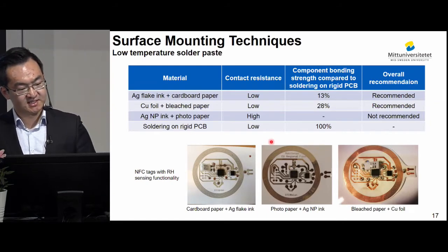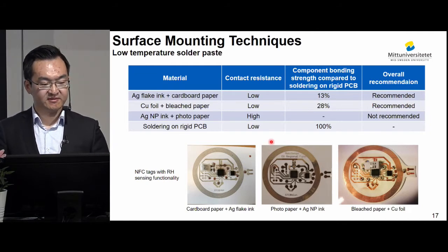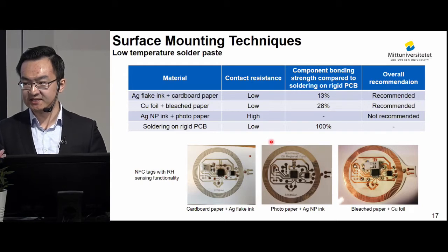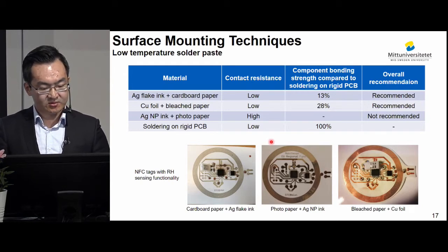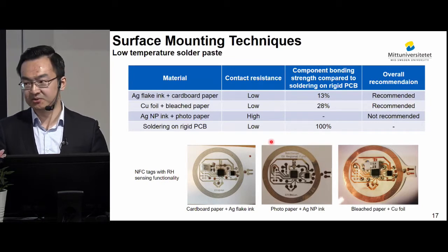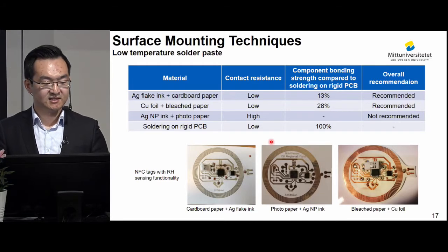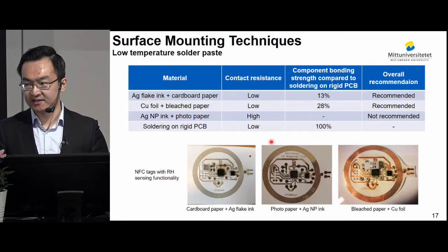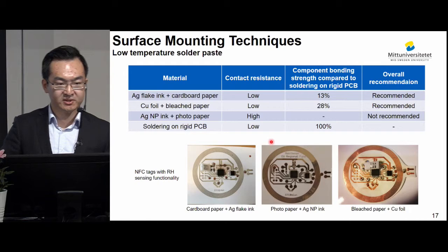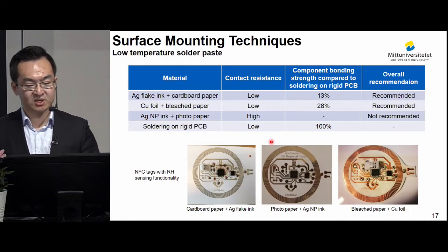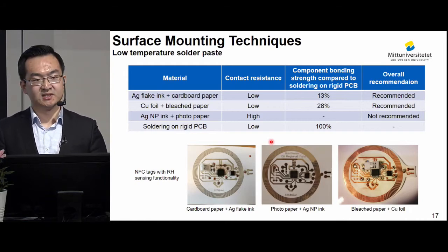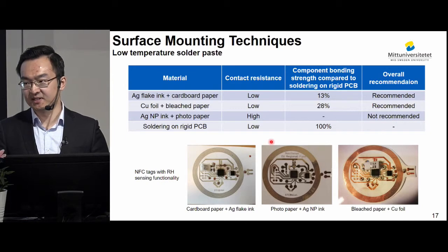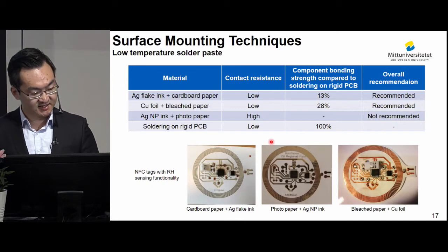And the components soldered on silver nanoparticle ink and photo paper showed high contact resistance, which was because of thermal expansion mismatch between the solder paste and the nanoparticle silver track and the photo paper coating material. In that case, we do not recommend this method to be used in implementing electronic systems.